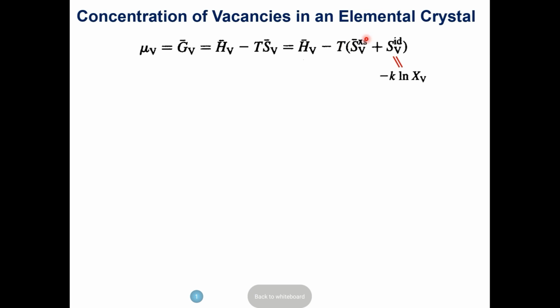But so that's the ideal term. It usually will come as Boltzmann constant times logarithm of the concentration of vacancy, and then an excess term—this is on top of it. As I said, if you have an interactive system, there will be excess entropy related. So you can go back and write the chemical potential of vacancy in the solid phase, with enthalpy terms and the excess entropy term—and this is for the ideal case, I just added that.